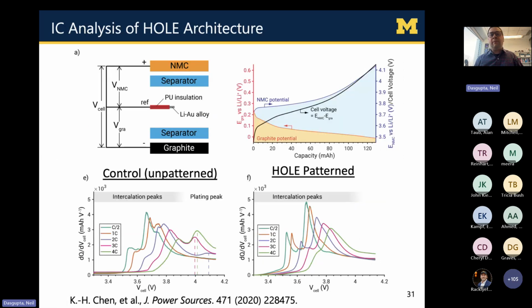We also in our group have been developing a lot of unique diagnostic probes. So one of the ones we really like a lot is utilizing a 3-electrode setup. So we're able to insert these micro reference electrodes into our pouch cells that allows us to decouple the voltage trace from the positive and negative sides of the battery. That's what you're seeing on the right-hand plot here. We can see independently under fast charge conditions what's the potential of the cathode versus the anode. And we're able to take the